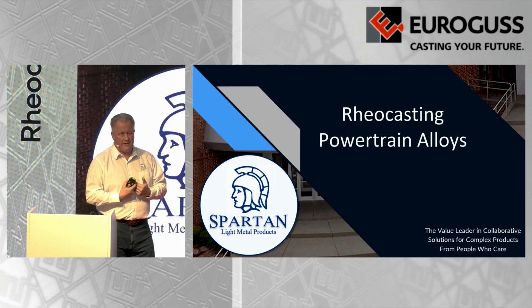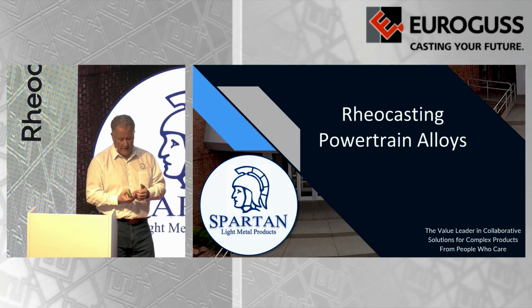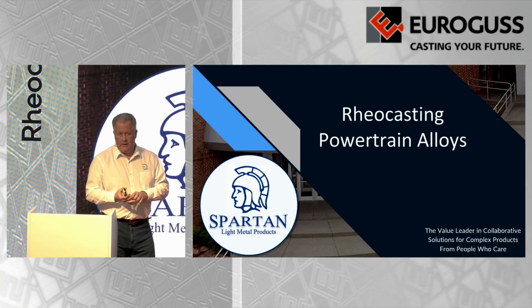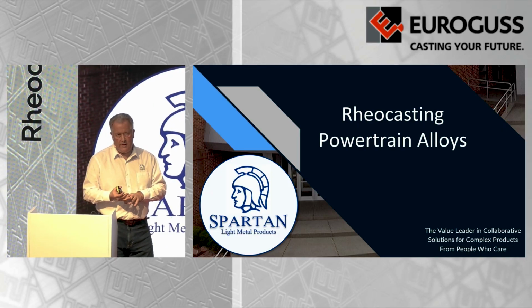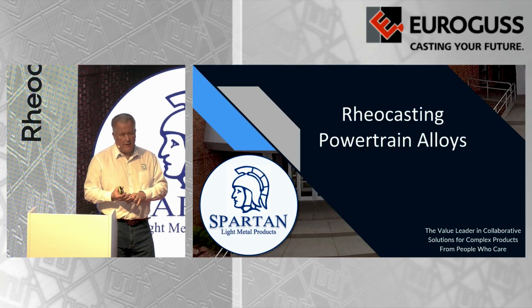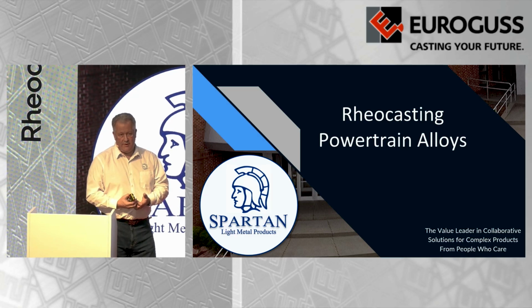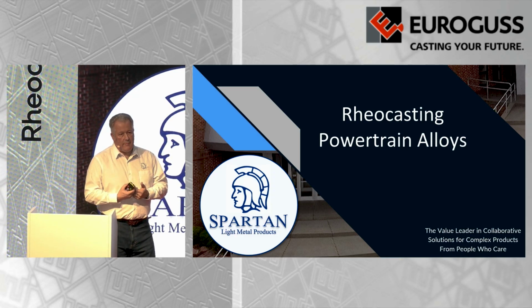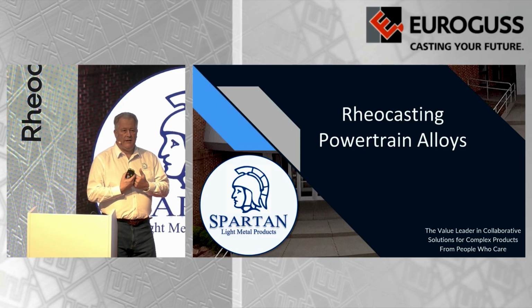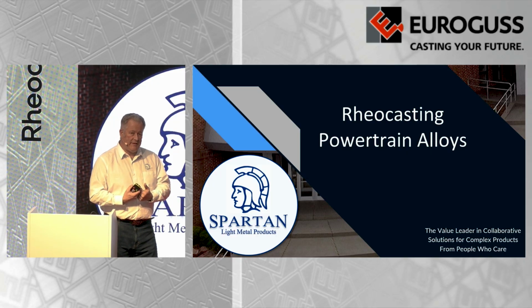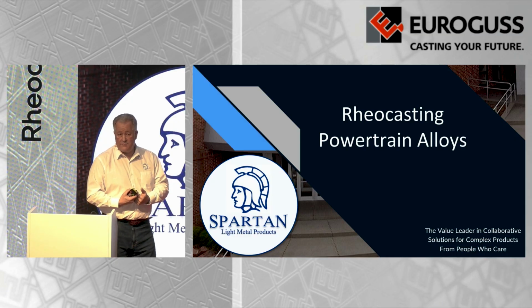And for us, we see two major benefits to that, one of which is tool life. Now, conservatively, we're being told that we can get twice the lifetime out of a die casting tool. And when you're looking at $250,000, $300,000+ for a tool, that's a really big deal. The other benefit is you can take a part that would traditionally go in a 2,000-ton machine, and put it in a 1,200, 1,400-ton machine. So the opportunity there to go multi-cavity is very attractive to us.